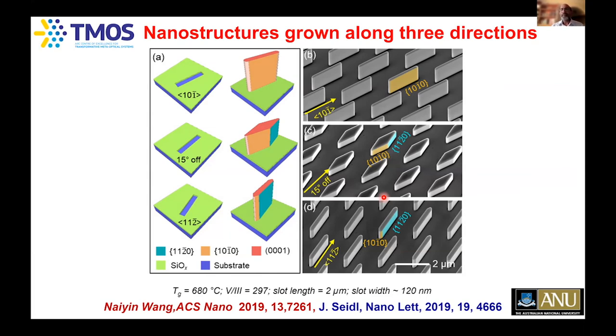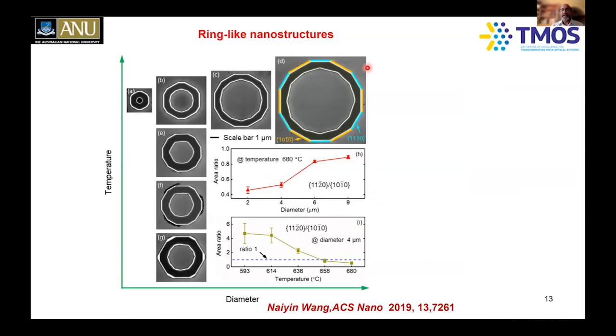So let's move to what will happen if you open a ring. Well, if you open a ring, and again, you really grow these structures, you can see you can create beautiful ring-like structures with these alternating facets which I've shown you earlier. Again, I won't go into the details of all these various parameters that Naiyin Wang has varied in order to get these nice and beautiful structures.